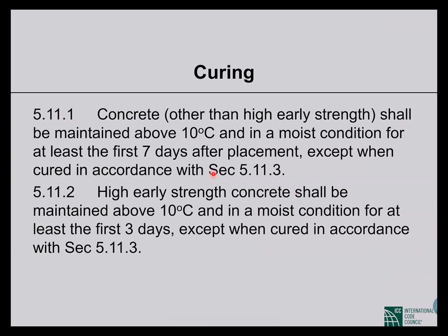Then let's talk about curing. Concrete other than high early strength shall be maintained above 10 degrees centigrade and in a moist condition for at least the first 7 days after placement, except when cured in accordance with other provisions. So usually in practice, we don't remove the props before 14 days. If we are sure about the early strength gain, then we can remove it earlier, but usually that is the practice. But according to the code, we must cure the concrete at least for the first 7 days, and we should maintain the environment so that the temperature is more than 10 degrees centigrade.